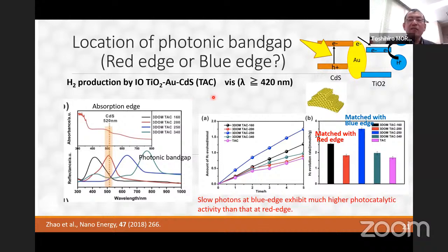In this composite, titania provides the three-dimensional ordered structure for better light penetration and mass transfer, while cadmium sulfide is the visible-light-responsive component. Gold nanoparticles serve as electron transfer mediators, like this. The slow photon effect occurred by tuning the macropore size of the photonic crystal skeleton from 160 nanometers to 340 nanometers to match the photonic band gap, here, and the absorption edge, here. This says 520 nanometers, okay?